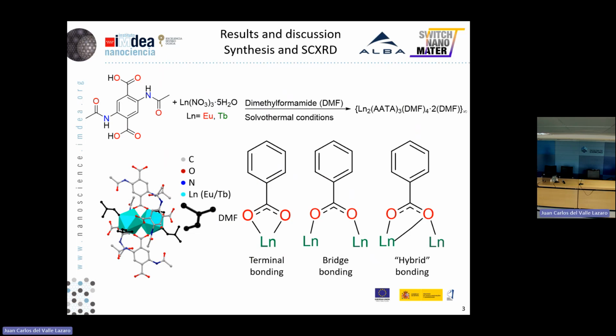Also, this material showed 3 different ligand to metal bondings. The first one was a terminal bonding with two oxygens coordinated to the same lanthanide, the bridge bonding with one of the oxygens attached to one lanthanide and the other one to the other lanthanide of the cluster, and finally a hybrid bonding between those explained before.